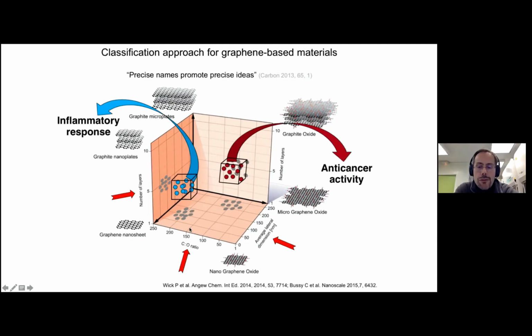So in that graph, coming from this publication, we've seen that there is a possibility to classify and to make some better ranking of graphene depending on the number of layers on the z-axis, on the amount of oxygen grafted, because many graphene come from reduced graphene oxide, and also the size of the sheet, here starting from 1 nanometer to a much longer size. And you see that in this three-dimensional space, there are already very different potential application and potential properties of graphene.